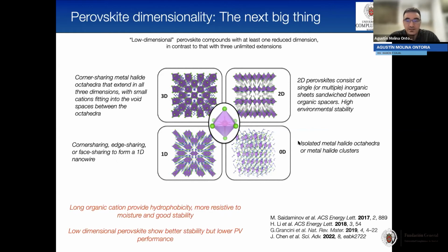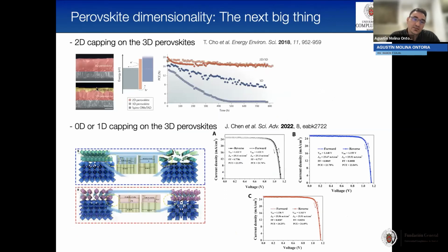The only problem with this is that the 2D perovskites are showing lower efficiency, but at least if we combine them, just like in this paper, as a bilayer, we can improve the stability in comparison with just the 3D, and even the long-term stability. Also, if we use these 0D or 1D perovskitoids in combination with the 3D perovskite, we can improve not only the photovoltaic performance, from 22% with only the 3D, to 23, almost 24, and here to 24.5%. But we are not only improving the efficiency, we are also improving the long-term stability.